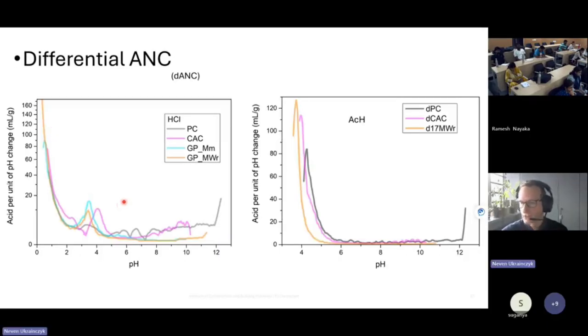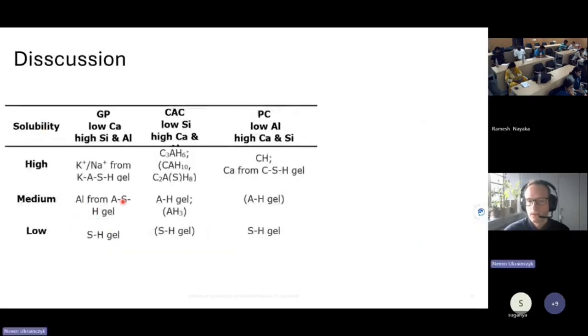Yeah, this is a differential derivative of the previous one. And here I'm just comparing the different amount of, what is the difference in the binders. Portland cement has a low amount of aluminates. You can increase this if you add metakaolin in LC3 mixtures. It has high calcium and silica, but those have very high solubility. In low and medium pH, silica gel is the one that stays in low pH, in the acidic range. You have alumina gel, but very little. So if you actually increase alumina, this should increase also the acid resistance.